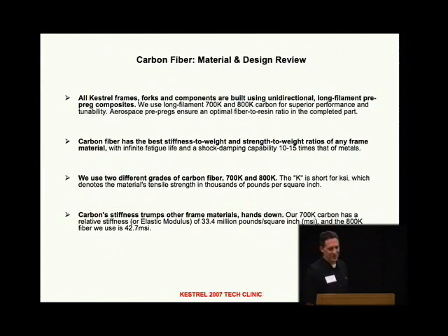This is a lot of words here, but basically the materials that we use to make frames come straight out of the military and aerospace industries. It's called carbon fiber prepreg. The prepreg means that the fibers are typically aligned along an axis and then coated or treated with a matrix material like epoxy resin. So prepreg means pre-impregnated with, in our case, the epoxy resin. I mean, literally, we were taking engineering material specs right out of aerospace and applying them to these bikes. And in fact,